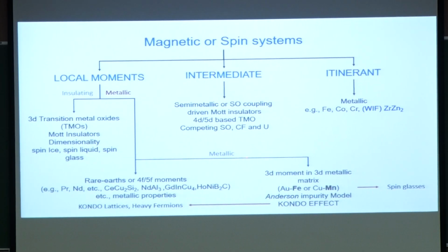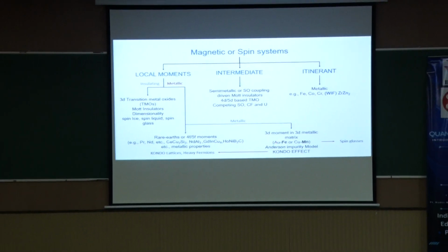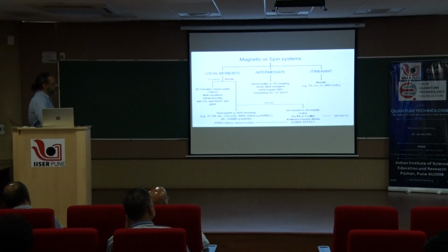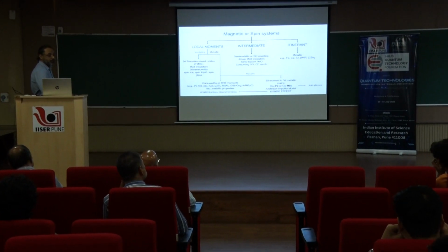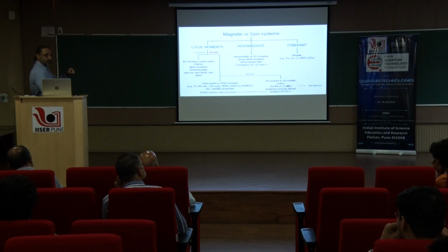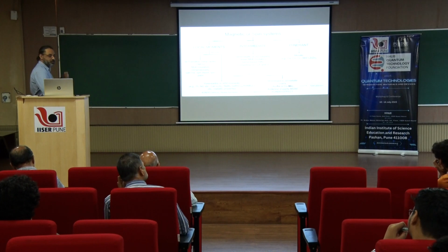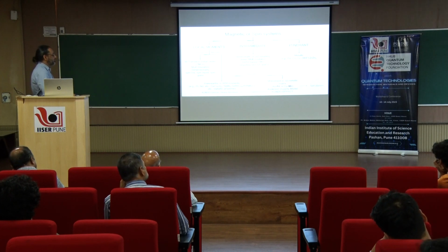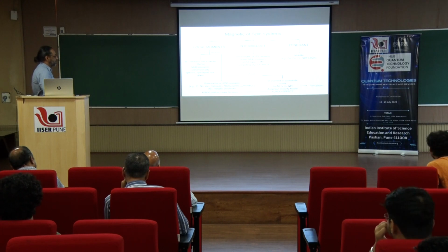And then you can also have local moments in situations like this. So, for instance, gold is non-magnetic, but you can put a tiny bit of iron in there. Okay, impurities, iron as an impurity. So, when iron goes into a gold matrix, it retains its magnetic moment, which is not always the case actually. Okay, so this was basically described by the Anderson impurity model, whether an impurity will retain its magnetic moment in a host metallic matrix or not. And in this situation, you see a many-body effect, which is known as the Kondo effect, which leads to an upturn in the resistivity at low temperatures, which means that the resistivity of the material increases upon cooling rather than decreasing or becoming a constant.